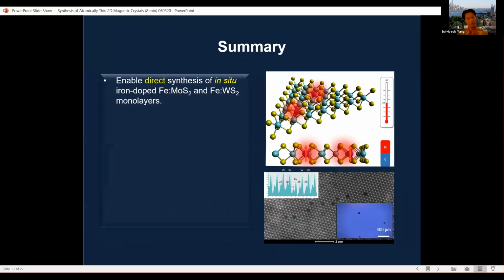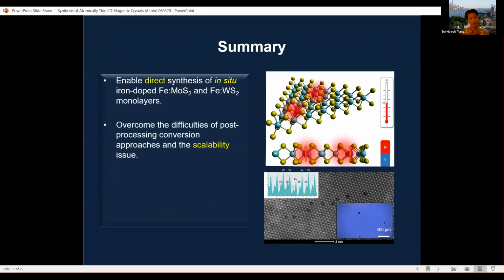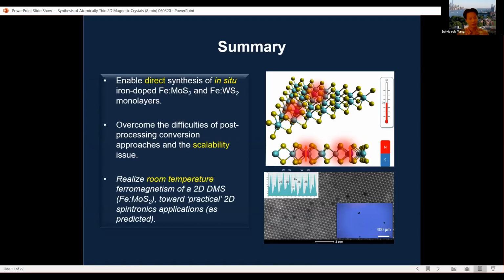In summary, we enabled the direct synthesis of in-situ iron doped molybdenum sulfide as well as tungsten sulfide monolayers, and we overcame the difficulties of previously reported results, like post-processing and scalability issues. We also realized room temperature ferromagnetism in the iron doped molybdenum sulfide, while iron doped tungsten sulfide doesn't show any ferromagnetism. That's an area of research we are working on now. Because these are room temperature materials, this is toward practical 2D spintronics applications in the future, as predicted by theory work.